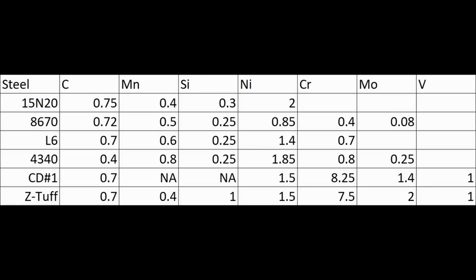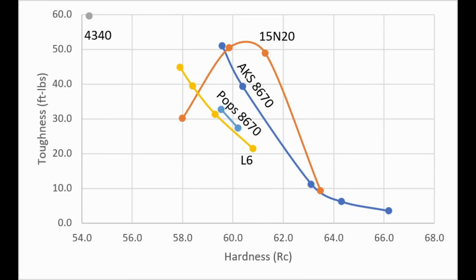Another steel I tested is 4340. This one isn't used in knives that much because it only has 40 points of carbon, which limits its potential hardness. But it has almost 2% nickel, so I thought it would be interesting to throw in here. As quenched, so I austenitized at 1550 and quenched in Parks AAA, I got 59 Rockwell, and after tempering at 400 degrees, I got 54 Rockwell. And the toughness was even higher than the higher carbon steels, as we might expect, about 60 foot-pounds. And so this steel could be useful for certain applications, maybe axes or swords, or applications that don't need really high hardness, but need really, really high toughness. They cannot fail through chipping or breaking.